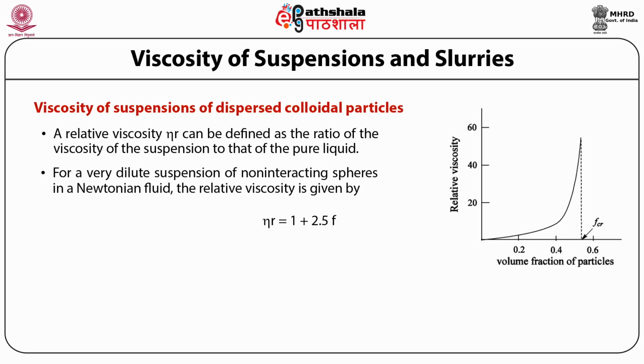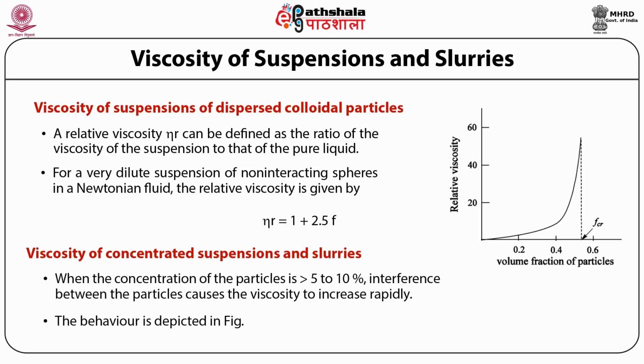Now, we will discuss the second case, that is, viscosity of concentrated suspensions and slurries. The equation which we have described above for relative viscosity is valid for dilute suspensions. When the concentration of particles is greater than 5 to 10%, the interference between the particles causes the viscosity to increase rapidly. The behavior of the concentrated suspensions and slurries can be described by an empirical equation which is given as eta r is equal to (1 minus F divided by FCR) to the power minus K, where FCR is the critical packing factor at which the flow is blocked and K is a parameter. The behavior can be seen in this figure.